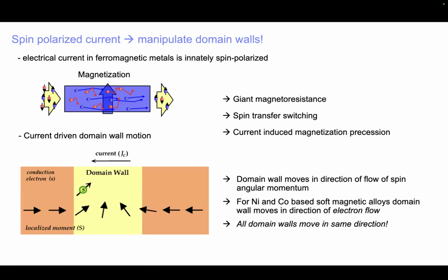And in the bottom left, you can see a simulation or a cartoon of what happens in a magnetic wire in which you have 2 magnetic regions pointing in opposite directions, and there's a magnetic domain wall in between. When you now pass a current of spin polarized electrons, magnetized but oriented in one direction, that current can deliver angular momentum to the moments in the domain wall, apply torques, and cause the domain wall to move. And interestingly, all the domain walls will move in the same direction in a single magnetic wire.